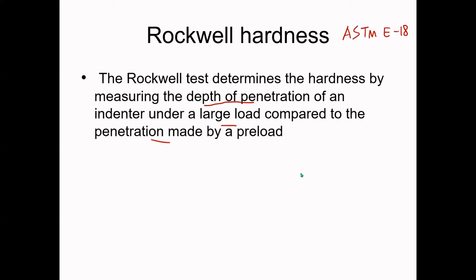Rockwell test is designed as a method of hardness testing for rapid comparative analysis between different types of materials or samples. The depth of impression or indentation is measured and rated on a dial calibrated inversely into 100 divisions. A deep impression will result in a low value, which implies a soft material. A hardened steel ball indenter is used with a diameter of 1/16 inch, 1/8 inch, 1/4 inch, and 1/2 inch, and standard indenting loads are 60, 100, and 150 kilogram.